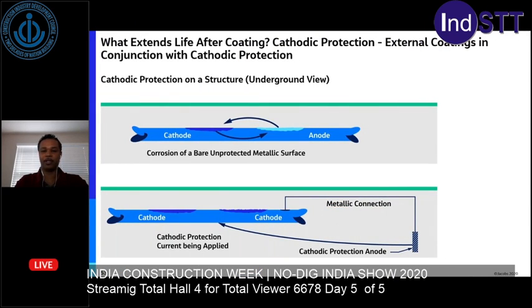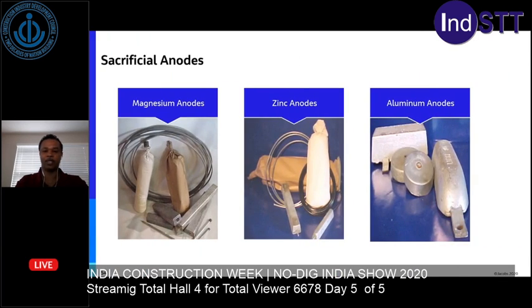So what extends the life after coating? You can consider adding cathodic protection. So the picture on top, you'll see where there's the unprotected bare structure that has both cathodic and anodic regions on it. So these regions are constantly interchanging, and this steel is trying to get back to being iron ore. So that energy is trying to release from that structure by being formed to get back to the native state of iron ore. And at the bottom, you'll see where a cathodic protection was added, where an anode was used. So the anode will corrode to protect that structure, which now becomes solely a cathode, and it becomes cathodic. And that is the reason for the term cathodic protection, because the structure being protected is cathodic, and the anode will corrode.